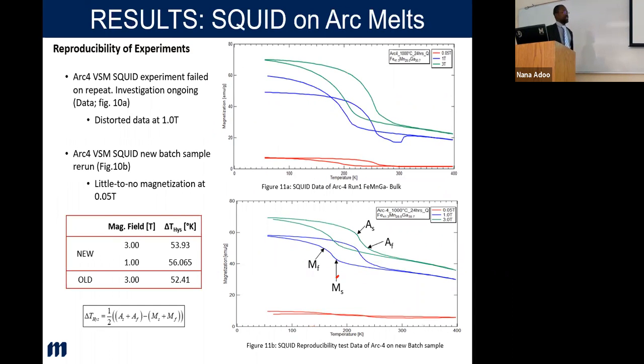So the arc melted samples for a pure SQUID showed one thing. This is a pure transformation for one of them. Another problem I saw was that you see these are two materials, two same materials, arc melted and everything. One SQUID failed, the other one did not. Why? Because there was a bug in the SQUID data acquisition, and to repeat the experiment, it failed again.